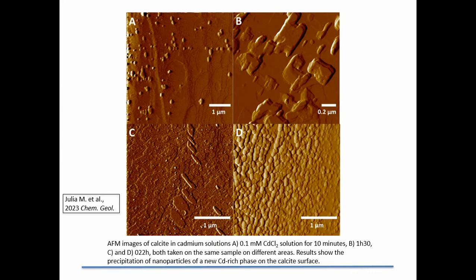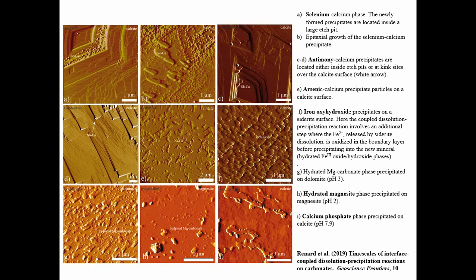Okay. This is jumping up to more closer to the future. This was some work of a doctoral student of mine where she was looking at cadmium on a calcite surface. We get the similar kind of thing. So you can see the formation of nanoparticles where we've got a small amount in millimoles of a cadmium solution on the surface, and we end up with the surface being covered with a new phase, and at the end it's a cadmium carbonate phase, otavite, which in fact actually covers the surface, and the reaction goes much more slowly after that.